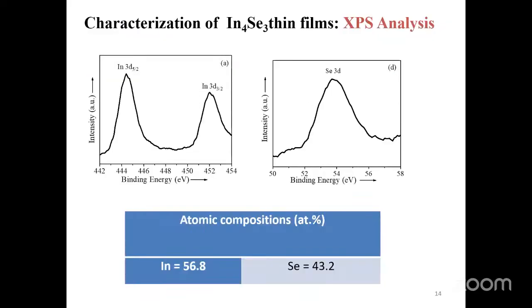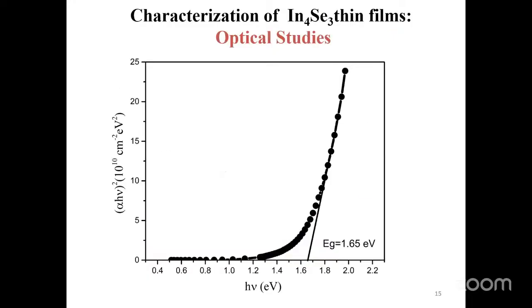This is the XPS analysis on the prepared sample. The sample shows an atomic composition of 56.8 for indium and 43.2 for selenium. This is the Tauc plot of the In4Se3 thin film. The sample shows a band gap value of 1.65 electron volt.